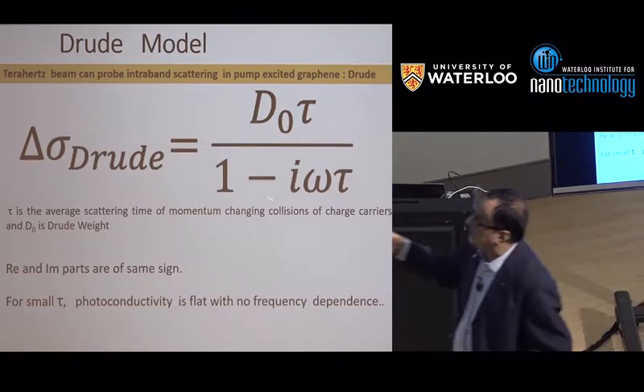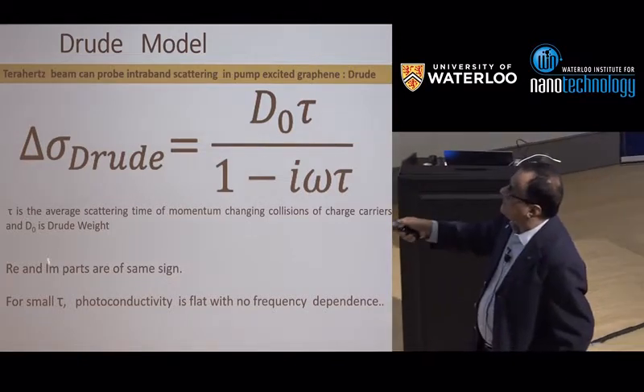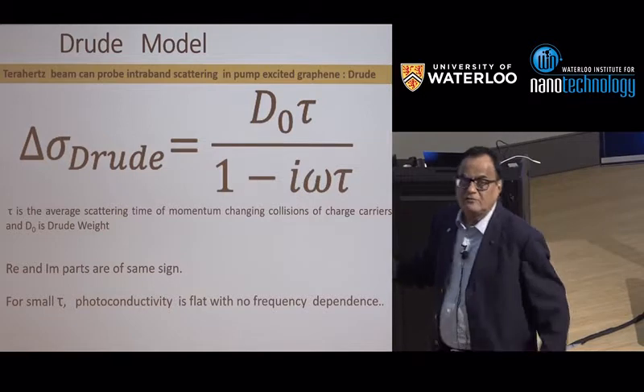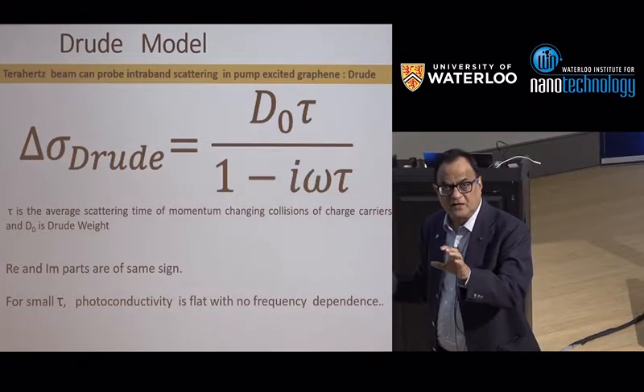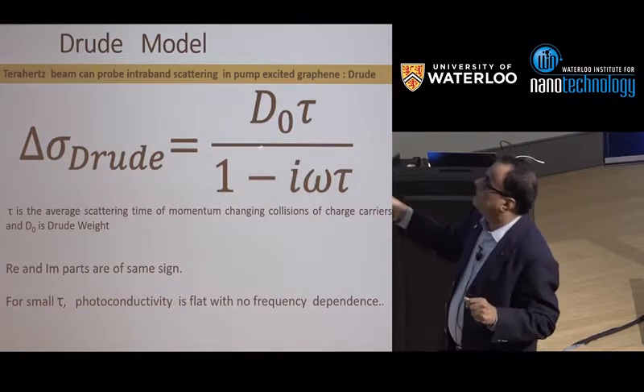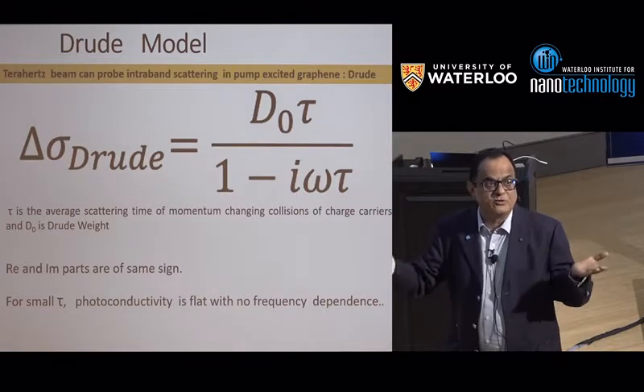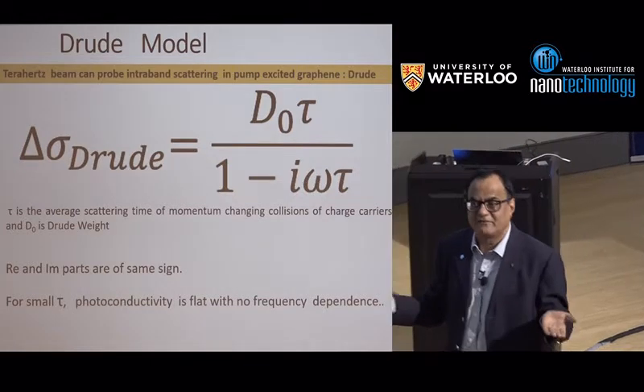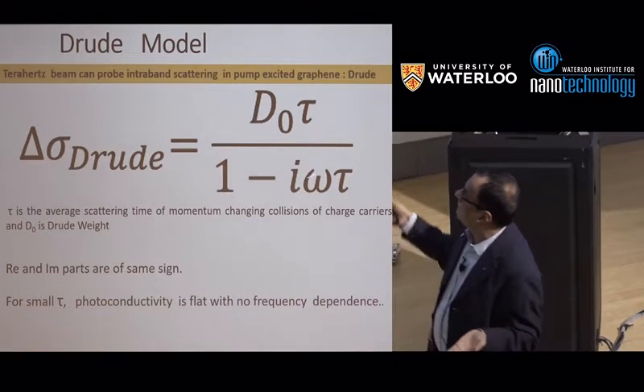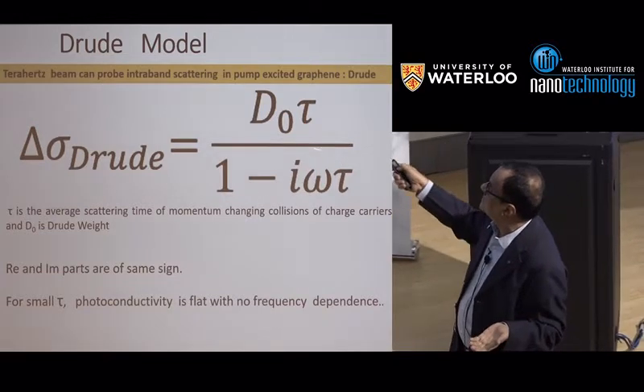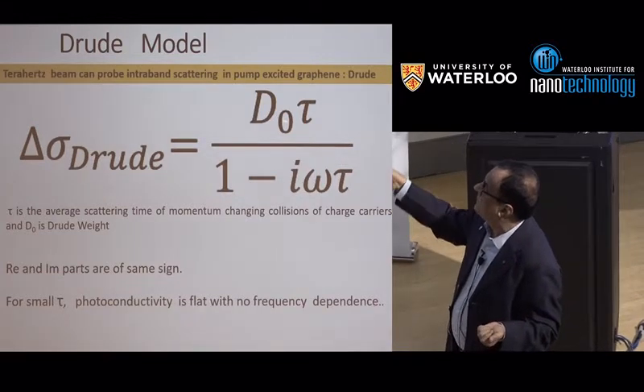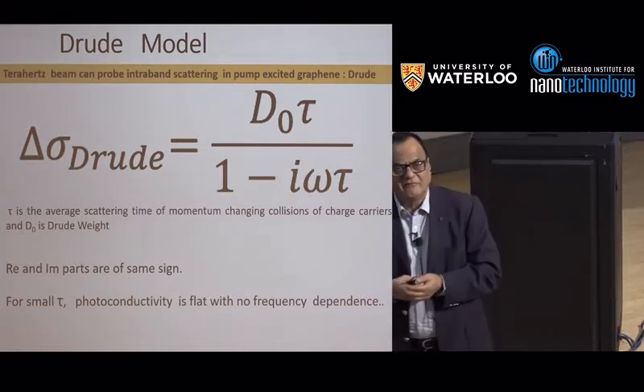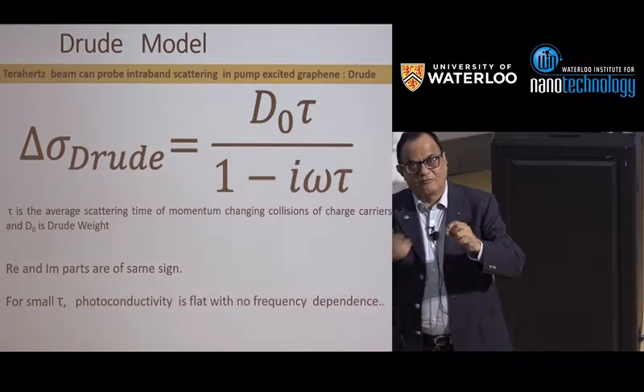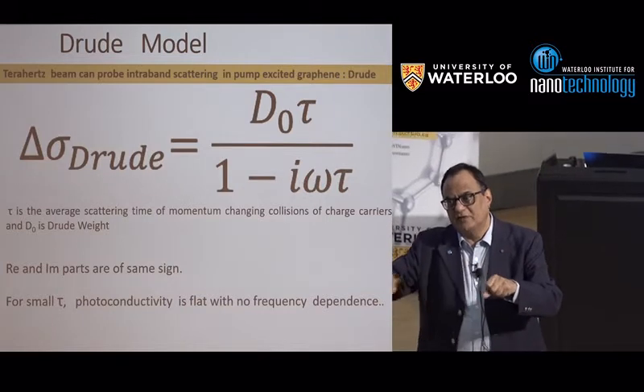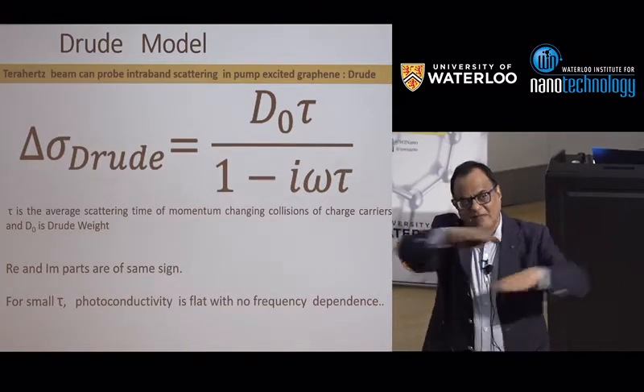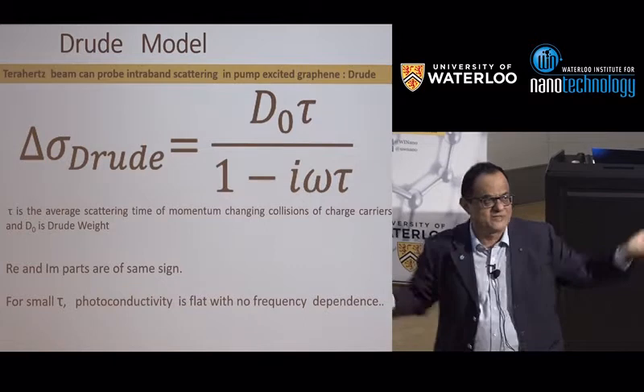But if that is the case, immediately you will see that the real and imaginary part of the photoconductivity, which we measure in the experiments, will have the same sign. There is no way to make real and imaginary part different sign. But at the same time, when tau is very small, this is negligible and this will be frequency independent. So you will get a very boring graph of conductivity change as a function of frequency, which is flat, and both are of the same sign.